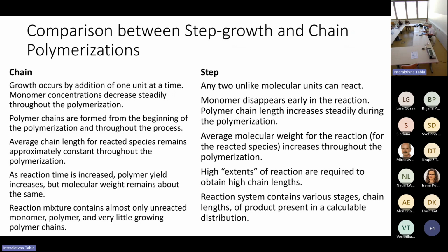While in chain polymerization, polymer chains are formed from the beginning of the polymerization and throughout the process. So in chain polymerization, we have high molecular weight already at the beginning. This chain length remains approximately constant throughout the polymerization, while in step polymerization, average molecular weight increases throughout the polymerization, and high molecular weight is obtained at the end. In chain polymerization, as the reaction time increases, polymer yield increases, but molecular weight remains about the same, as we already mentioned.